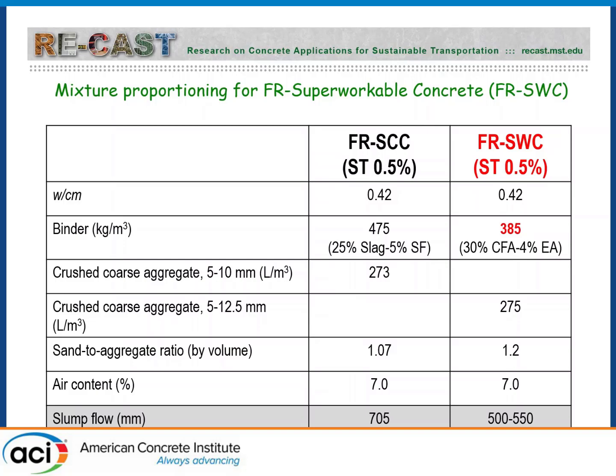So both of them are air-entrained concrete. You can see the fluidity is very different. So this would be about 30 inches. I'm converting on the fly here. This is about 20 to 22 inches slump flow.